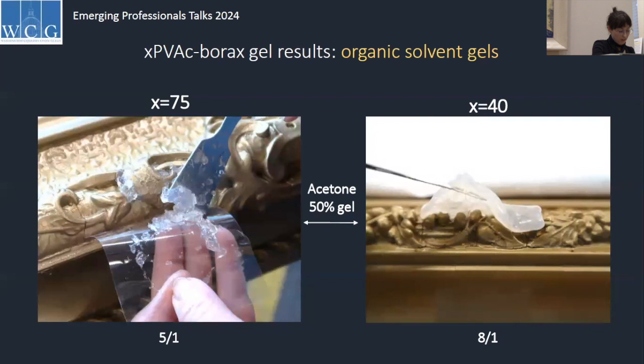So the successful formulation of organic solvent gels that exhibit desirable working properties, we really noticed was greatly affected by two factors in particular. That was the degree of hydrolysis of the polymer and the organic solvent that we're putting in the system. You can see here on the right, there's a 75 PVAC polymer and acetone gel on the left, and then there's a 40 PVAC polymer acetone gel on the right, and you can see that there's a real difference in the morphology of the gel, and that's really evident that the 40 PVAC is best suited for organic solvent gels.